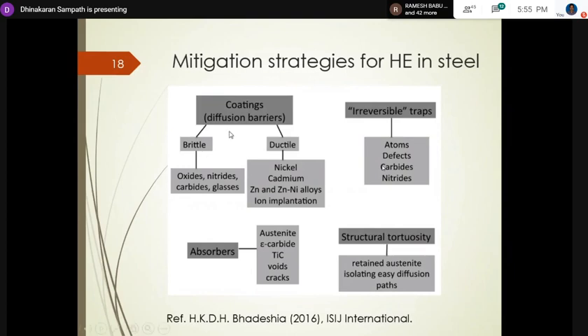Moving on to mitigation strategies. Here, I just populated the mitigation strategies for steel. This was done in one of the review papers by Harry Bhadeshia. He says there are about 4 different strategies one can follow to reduce the embrittling effects. One is coating, to just restrict the entry of hydrogen. And irreversible traps. That means they can use substitutional atoms or some defects, carbides, nitrides in the matrix, so they will just absorb the hydrogen and not release it.